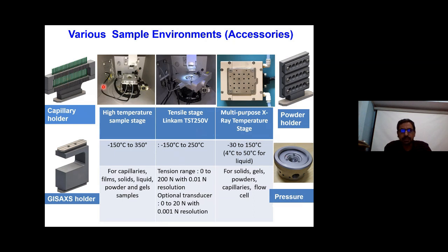We can put liquid samples, we can put solid samples at high temperature. We can actually take fibers and we can stretch them and do analysis on that. We can go from minus 130 to 150 degrees Celsius. We can take powder samples. We also have pressure cells. For example, if you want to see if pressure changes the properties or structure within your sample, then we can do all these things. And so far these examples are for scattering in the transmission mode, but we can also do it in the reflection mode, where when you want to analyze what is on the surface, you can use GI-SAXS, which is known as grazing incidence small angle X-ray scattering.